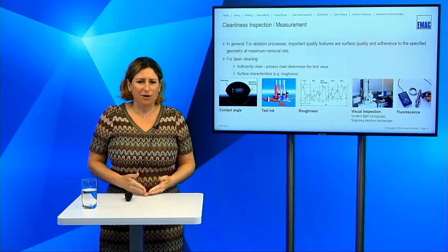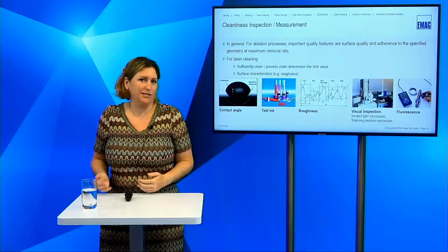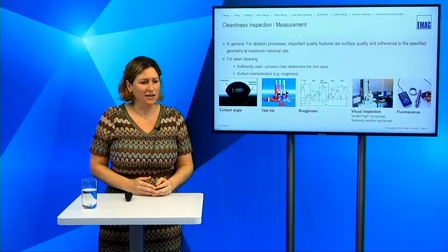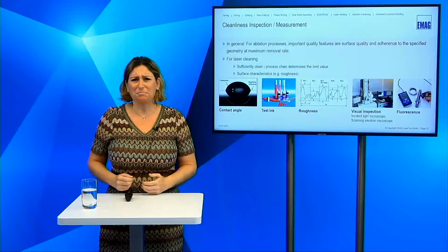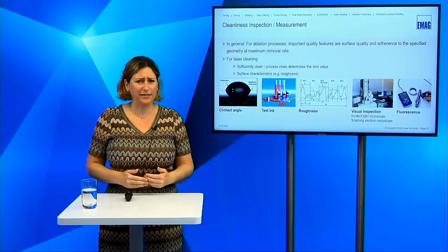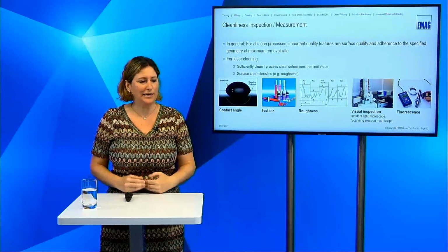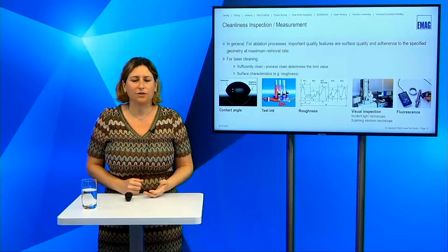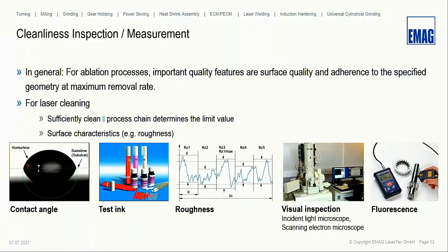But for laser cleaning, it's quite hard to say when it is clean. What is clean? You have different methods to check. It's only an indirect method to measure the cleanliness of a surface. You can use, for example, the contact angle measurement. You put a drop on the surface, and for a contaminated surface, you have more spreading of the drop, thus a low contact angle. And if you laser clean it afterwards, you get a high contact angle, an increase of the surface energy, and the drop looks more like a ball.